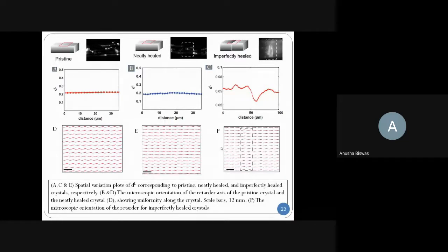Here the spatial variation of delta L in the crystal is shown for three crystals: the pristine crystal, the neatly healed crystal, and an imperfectly healed crystal. For the pristine crystal, the delta L value is not changing with distance. In the neatly healed crystal also it is fluctuating very little, but still comparable with that of the pristine one, confirming the perfect alignment of the broken faces. But in the case of the imperfectly healed crystal, it is fluctuating at a higher rate, which reveals the misalignment of the fragments at the crack position.